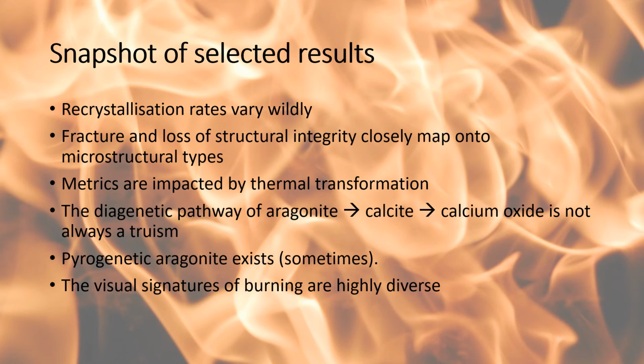Although the literature sometimes provides the following transformational pathway: aragonite transforms to calcite, transforms again to calcium oxide, we noted that this does not always happen. Differences in pathways were noticed when the same shell was modified via heating rather than via burning. Same temperature, 600 degrees in an oven versus 600 degrees on hot coals, you got quite different effects. And certainly in an oven, there wasn't a clear progression, always to the calcium oxide, to the most reduced phase. That's probably really poor chemistry terminology.